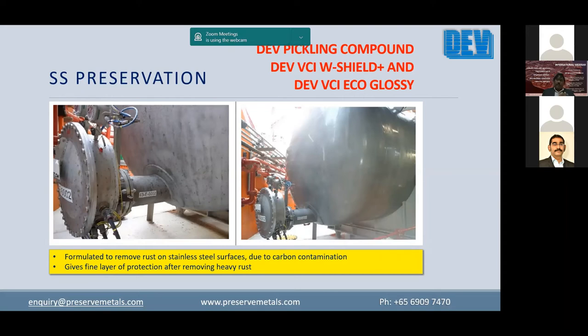This product was developed after an experience with one of our shipyards here, where after the rust removal we had used another, oil-based product, which was oily to touch, and they preferred to have a dry surface. This DEV VCI Eco Glossy dries very quickly, and as a result you are able to have a completely dry surface on the stainless steel piping and vessels.